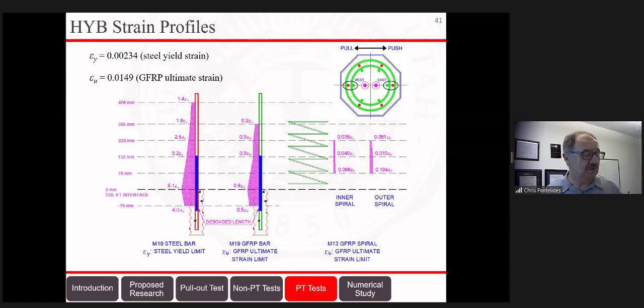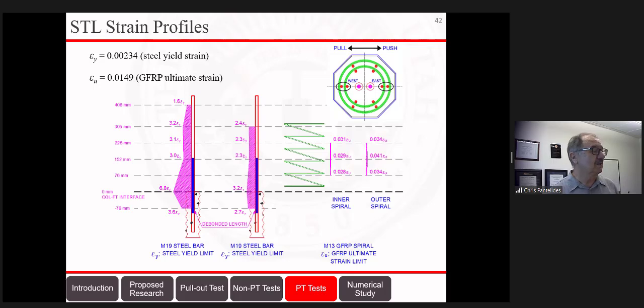And you can see here the strain profiles in the hybrid column. They were smaller, of course, than the profiles for the ones without post-tensioning. And that's because post-tensioning takes a lot of the force. So the steel reached 5 times the yield, but the fiberglass was only 60% of the ultimate. And the spirals, they were much lower. The strain only about 10% of the ultimate. So this completes the experimental part, which shows that we actually did what we wanted to do. This shows the steel profiles. This was a little higher because we had achieved more energy, so about 6.8 for the steel bars, the outer ones, and the inner 3.2, and the fiberglass about 3%.